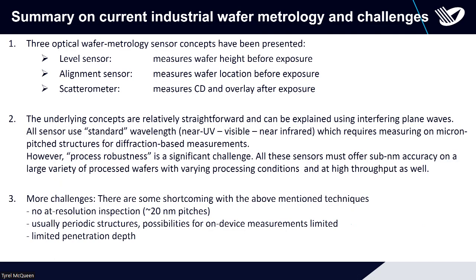So we've now gone through the main techniques used in semiconductor metrology: level sensor, alignment sensor, and scatterometry, both for CD and overlay. They're pretty straightforward concepts that all come from interfering plane waves. It's all with standard wavelengths, mainly from the near UV and visible to near infrared. But it's a significant challenge to measure robustly with that. Sometimes you have layers that bury your actual metrology targets. These computational approaches and scatterometry are often not very unique in the solutions that are found. So there are a lot of challenges.